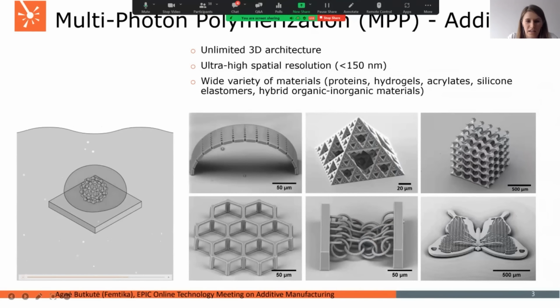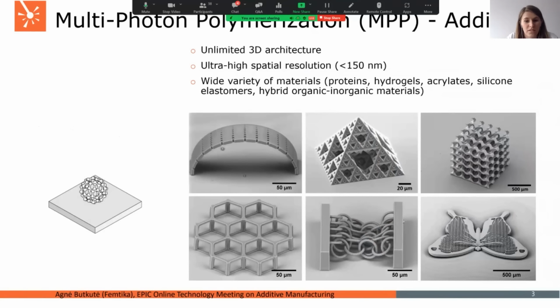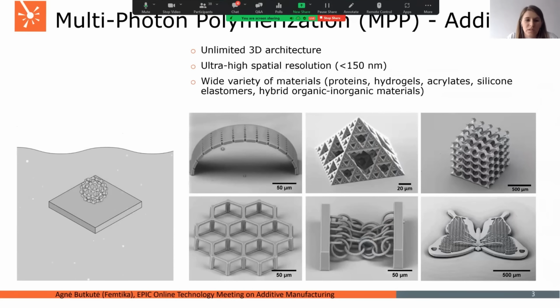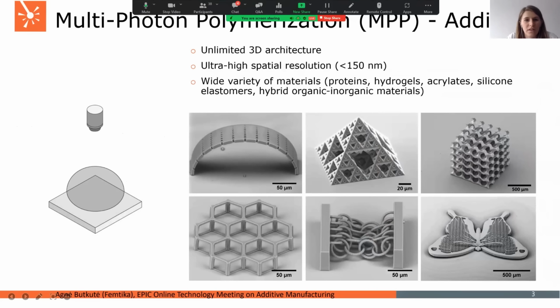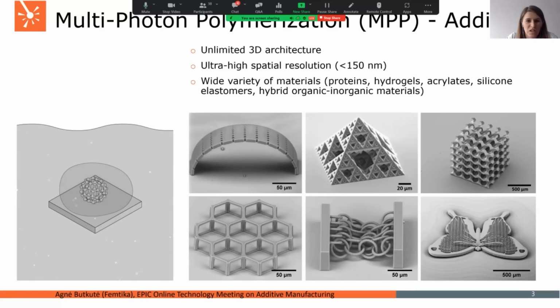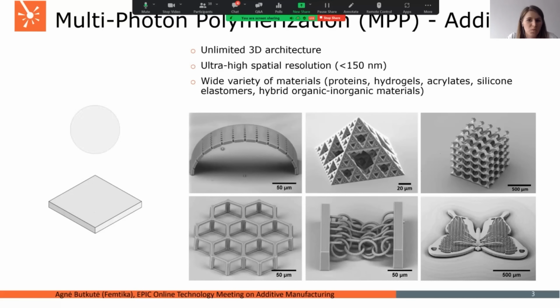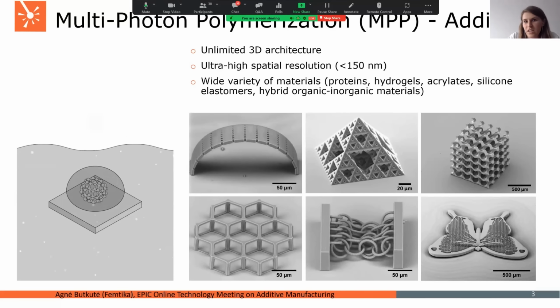You can see in the animation that just by using a focused laser beam, we're able to inscribe modifications in a polymer drop. In general, we're polymerizing material in the volume. Later, we need to develop it by using organic solvents, and in that way, we're able to produce unlimited 3D architecture structures out of various polymers, which can have quite high spatial resolution, up to 150 nanometers. As you can see, the possibilities of 3D architectures of the structure are quite wide.